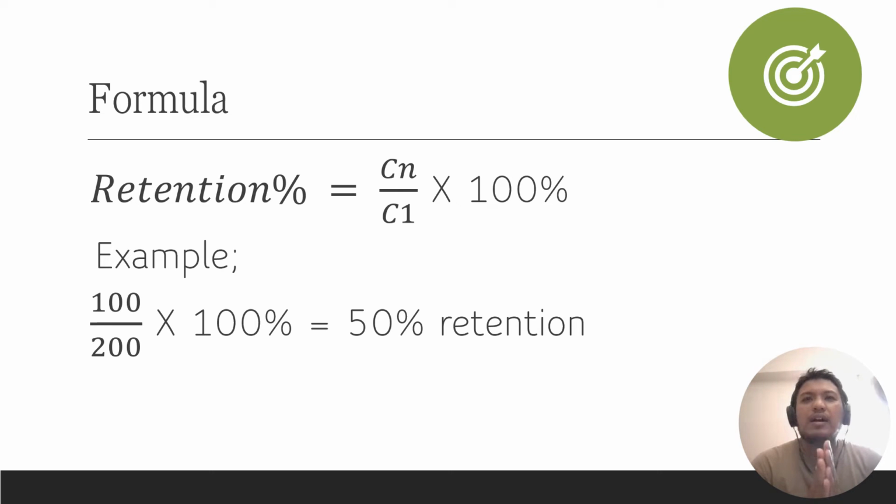So imagine you run a stability test for 10,000 cycles and you want to make a point every 1,000. What you can do is calculate cycle number 1, how much the specific capacitance is, then cycle number 1,000, 2,000, 3,000, 4,000, 5, 6, 7, 8, 9, and 10,000 cycles. Then you can get the retention values. You can see whether it slightly increases or gradually decreases. Everything has its explanation. Maybe if at the first cycle it increased and then dropped, it's because of the activation and wetting process, depending on your material. If your sample shows a normal behavior like slowly degrading, it's quite okay also. It depends on your material and the mechanism of what happened. So this is the formula to calculate.